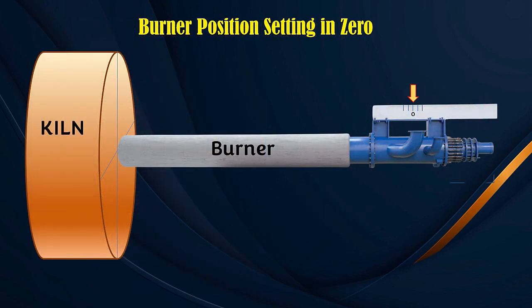Method three — prevention: so that there is no coating on the burner tip, set the burner position to 0 at the kiln outlet in the axial direction, or parallel to the nose ring. This means that no material will fall to the end of the burner when the kiln rotates.